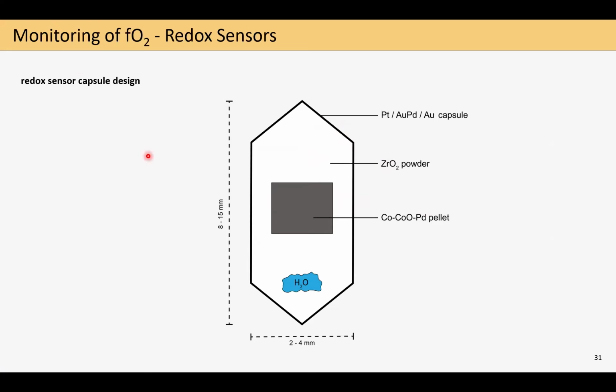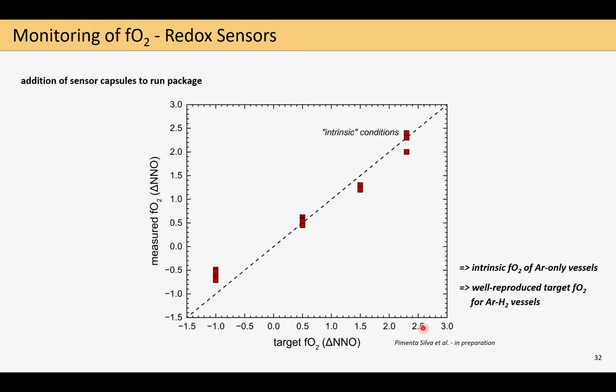Now let's come to what we did recently. You can monitor your fO2 conditions by just adding such a redox sensor capsule to your experiments. We did this in a recent study, where some of the people involved are also in the audience here. We were first able to measure the intrinsic fO2 conditions of our argon-only vessels, where we obtained an fO2 of around NNO plus 2.3. It also allowed us to check how well we could reproduce the fO2 conditions with the argon-hydrogen mixtures in these vessels, and you see here that this worked quite well. I think this shows that our general approach of buffering fO2 in our IHPVs is working.